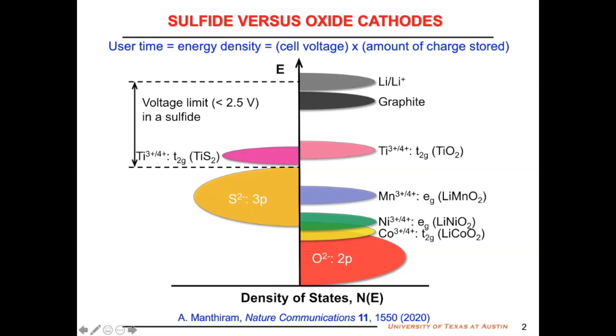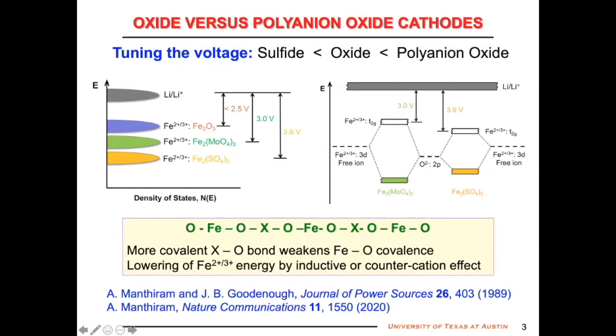With 30 years of experience and expertise on oxides, Professor John Goodenough at Oxford started working on oxides because the oxide 2p band lies at a much lower energy than the sulfur 3p band, so you can get 4 volt. So that's how all the oxide cathodes started. So when you go from sulfide to oxide, yes, you can increase the voltage from say approximately 2 volt to 4 volt. Now when you go from a simple oxide like Fe2O3 to a polyanion oxide such as iron sulfate or phosphate or even silicates,